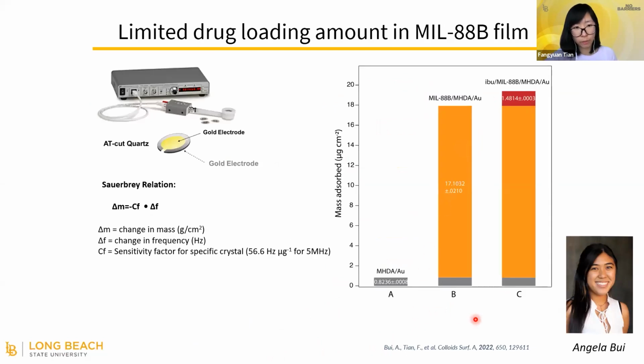So she used a quartz crystal microbalance to look at the drug loading amount. We found that after the direct crystallization process, around 17 micrograms per centimeter squared of material has been loaded on top of the gold sensor. And after exposure to ibuprofen, there's about 9 weight percent of ibuprofen loaded to MIL-88B, compared to 20% for the powder. This drug loading amount is about half of the ibuprofen compared to the powder. So we believe that's because we have limited surface area. All of the crystals have been attached or fixed on top of gold. So that's why it caused a 9% drug loading amount.